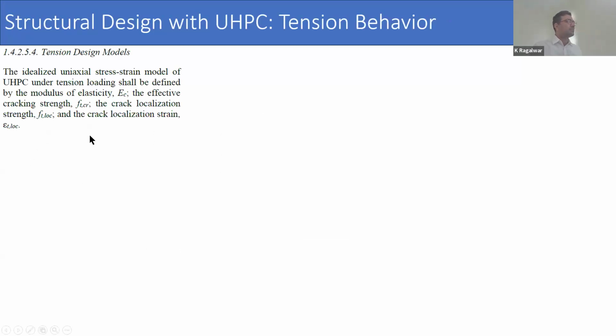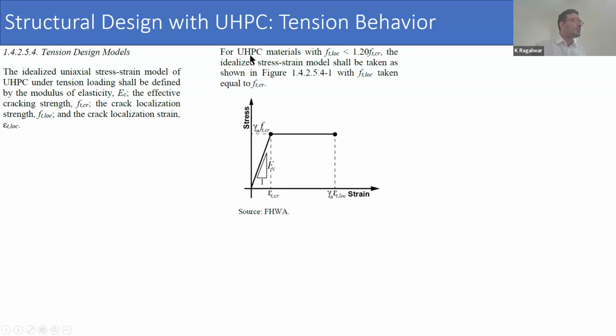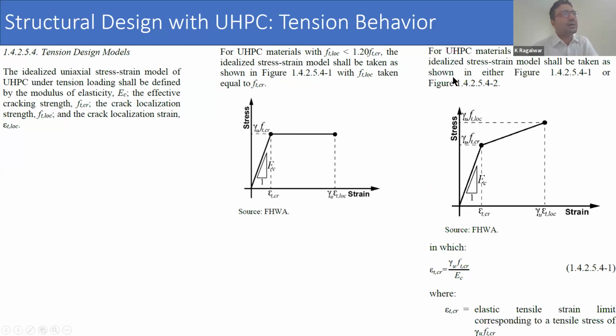Okay, so those are the parameters that we use to define the tension design model. There are two tension design models here to account for strain hardening. With UHPC materials where the localization stress is lesser than 1.2 times the cracking stress, we use the bilinear model with elastoplastic behavior. So we cap the stress limit at factored first cracking strength, and then that stress block is extended up to a factored value for localization strain.